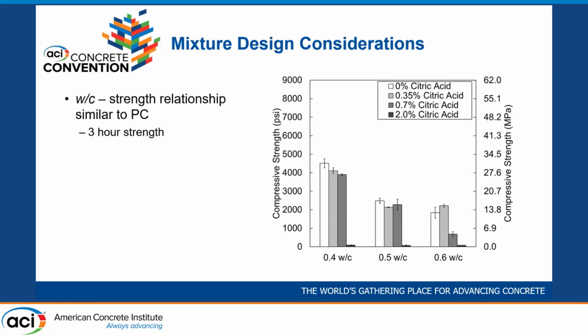When we go up to 2%, which is probably far higher than you would ever use in one of these mixtures, that's taking you way out to like Portland cement setting times. There's obviously no strength at 3 hours. But just like Portland, there's a relationship between water cement ratio and strength of the mixtures that's quite similar.